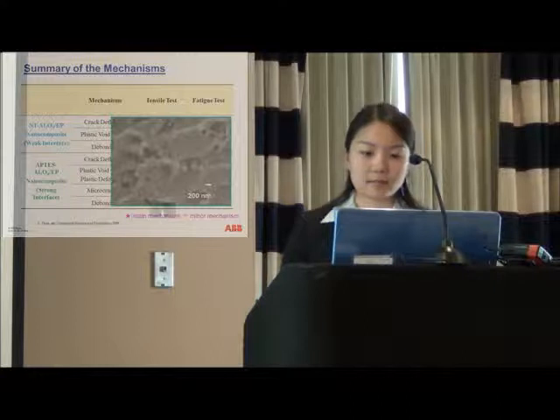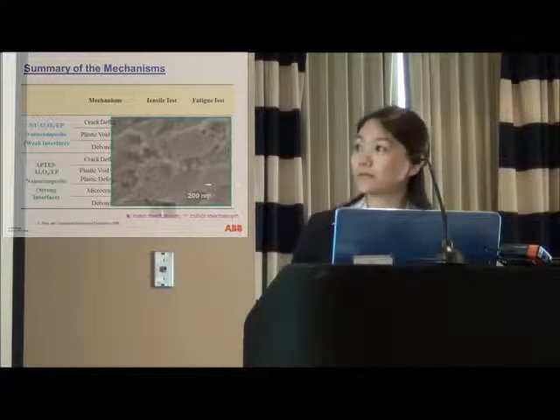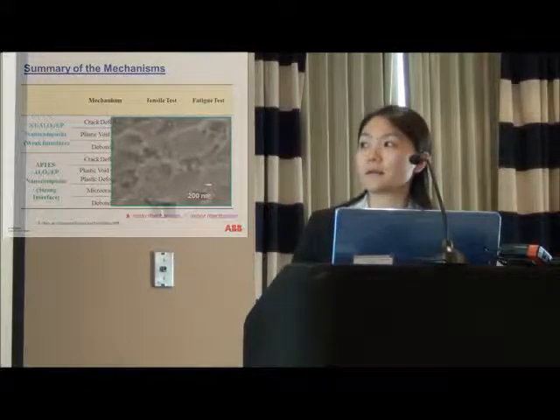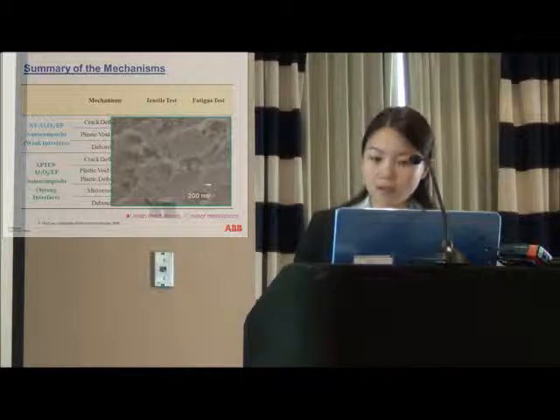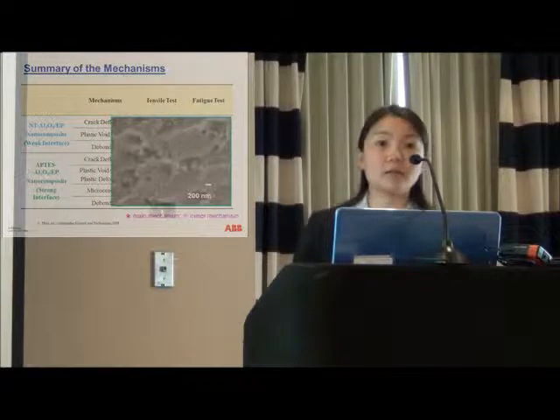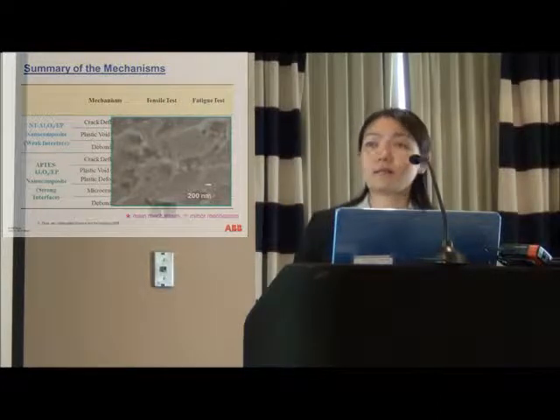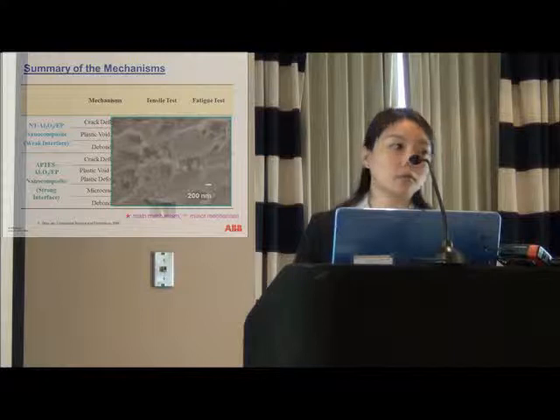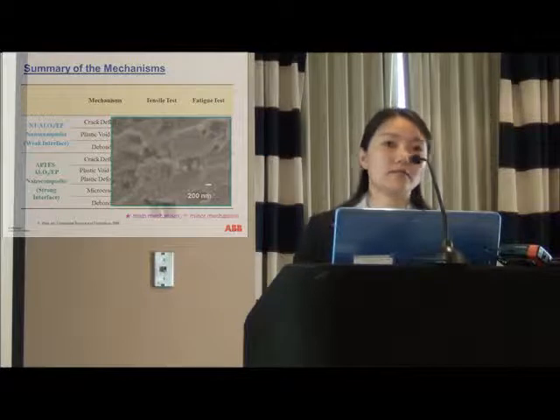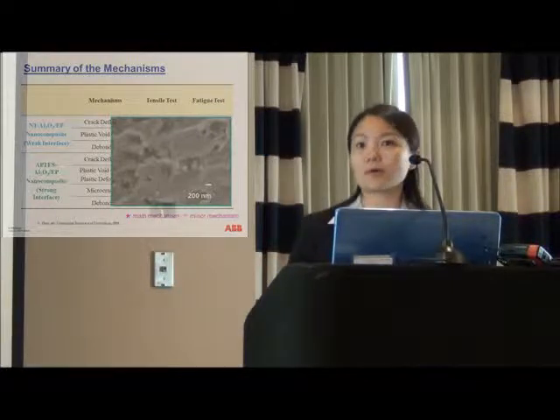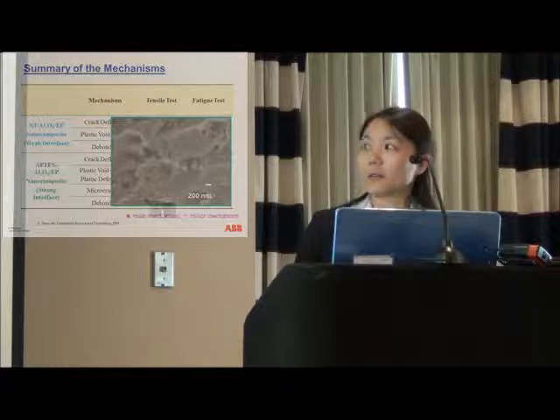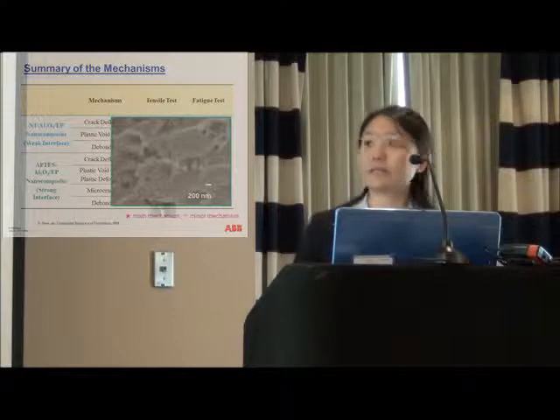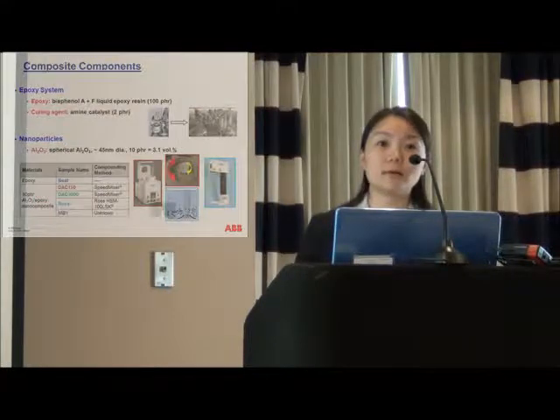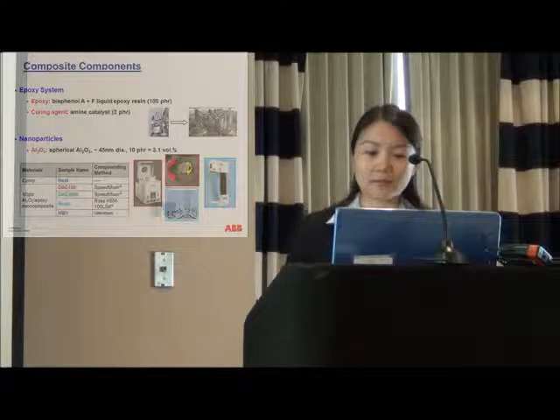Another interesting mechanism we noticed was for the treated particle filled nanocomposite, we saw plastic deformation around particles. That's something we've never seen with non-treated particles or pure epoxy - those just have very straightforward cracks. For the treated one, during the fatigue test, we noticed some plastic deformation.